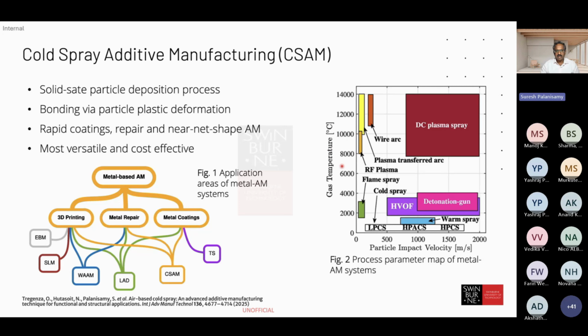That is where HVOF also is, and quite a lot of thermal spray technologies are used for hard metal coating applications, ceramics, or a few different high temperature, high melting point materials. However, cold spray is the process where you don't heat the powder particles, because usually in thermal spray, the powder particle is heated with high temperature gases. That is how they're propelled.